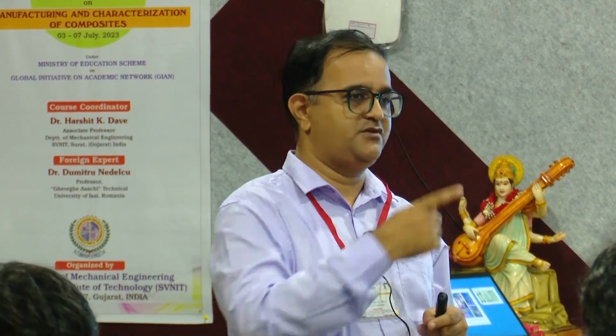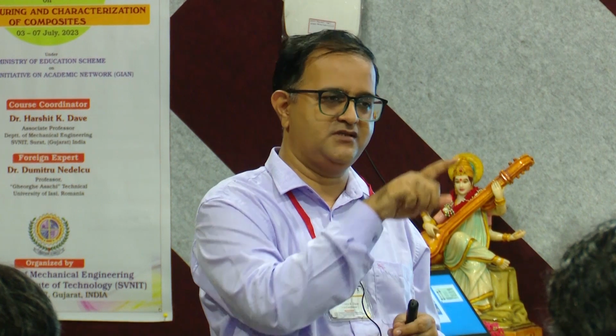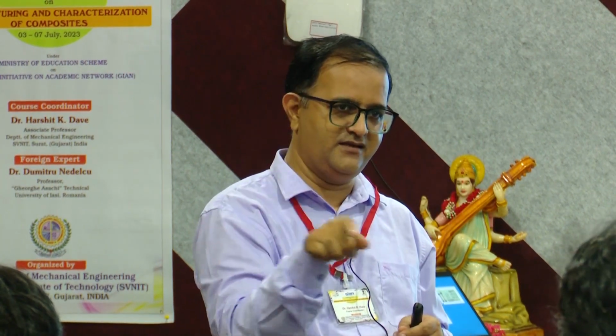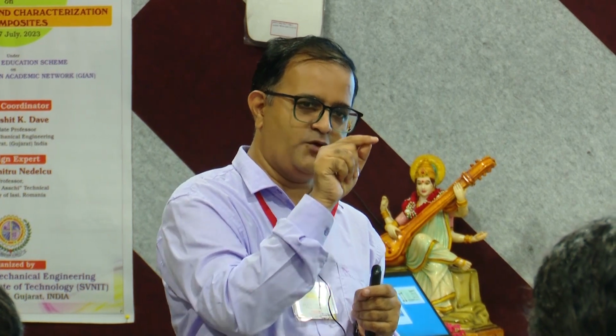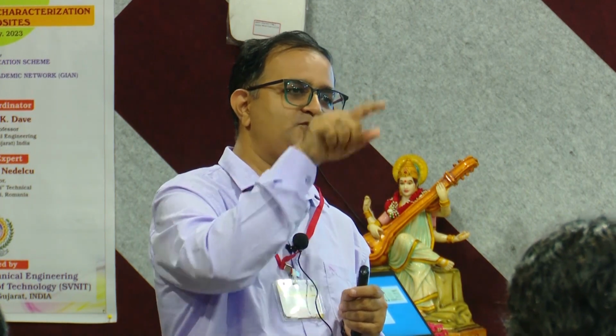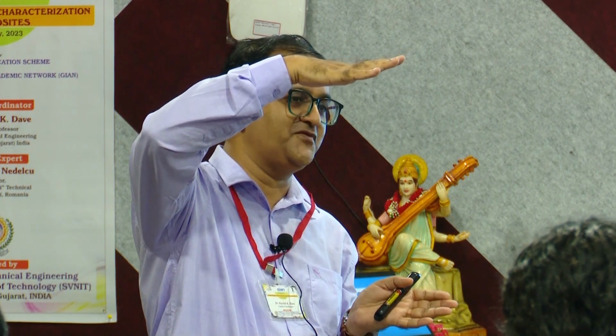And it was interesting when we tried to study the same for 3D printing. Now if you remember, we talked about the process, we can put up those rings at the periphery, 0 to 5 rings, if you remember I had discussed. Now incidentally, if I select 5 rings, it understands that rings are to be placed at the periphery. So when you put a hole in the center of an open hole test, it considers that also a periphery and puts 5 rings over it. Now when there are 5 rings over it, it reaches both the extremes of the part. So there is no place for you to place those 0, 90, 45 degree inclinations. So for that particular case, we changed our strategy and we reduced that 5 number to 3,